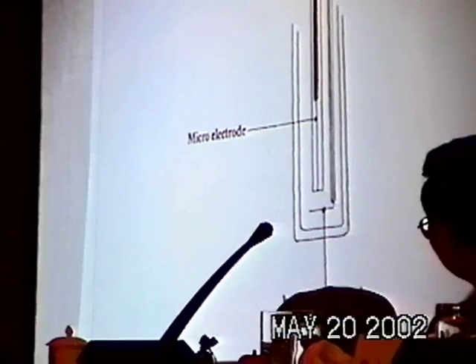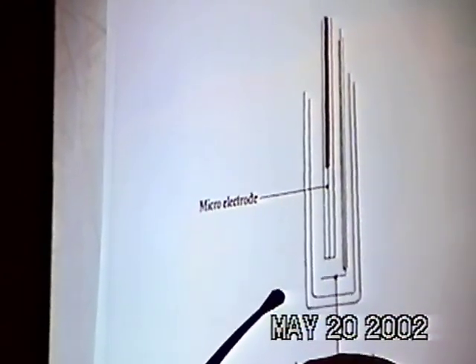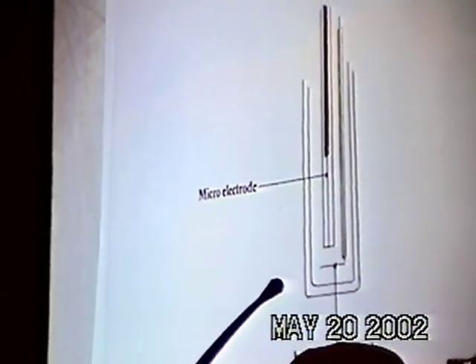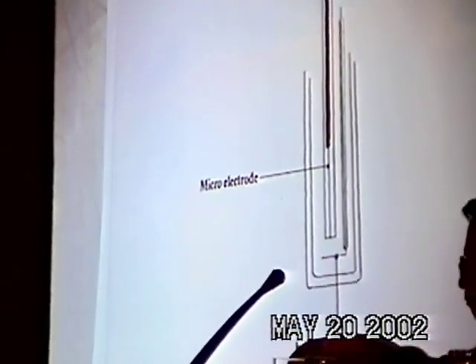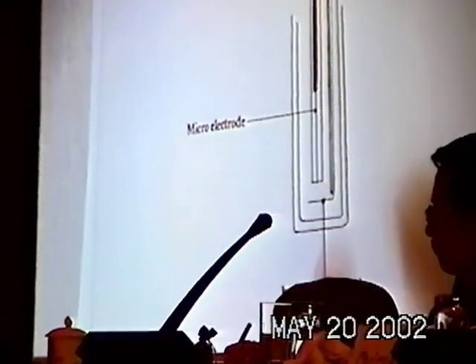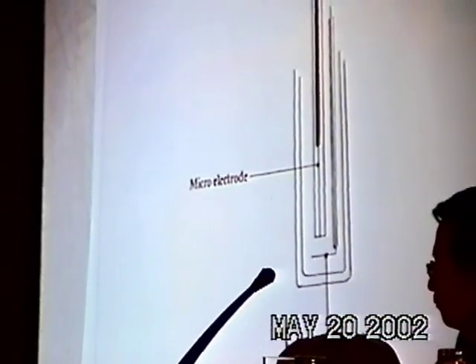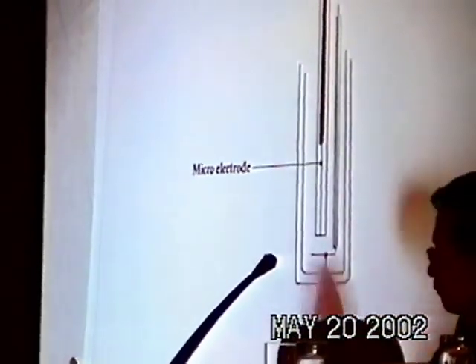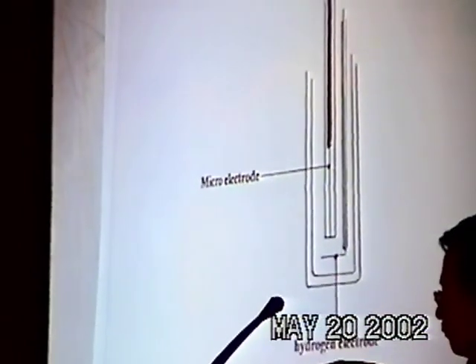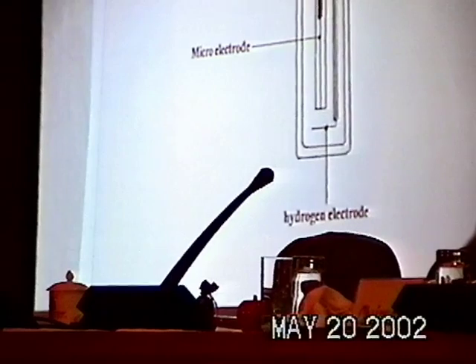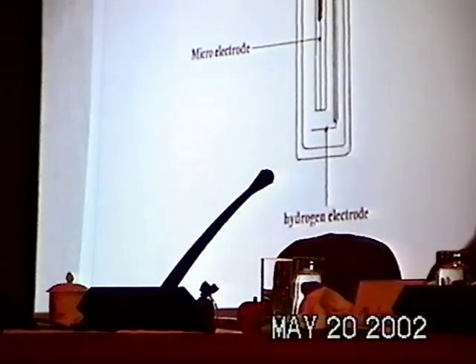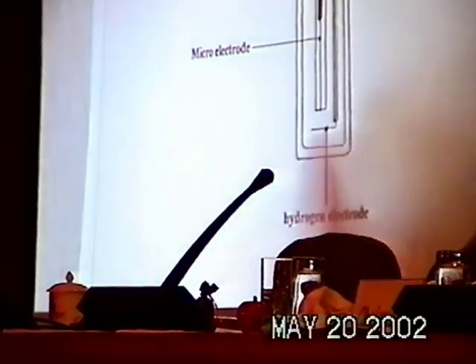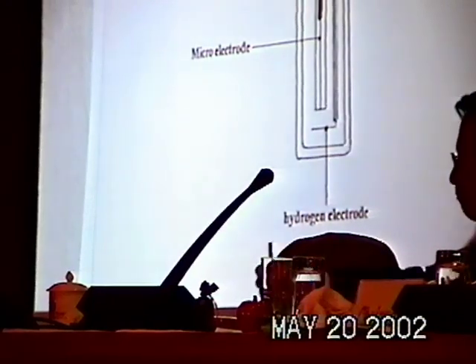The reason, of course, is that if you have a microstructure, then the joule dissipation of heat is reduced by orders of magnitude compared to a planar structure. So if you have an array of microstructures, you will get a much lower input of energy, and the excess energy will become much more visible. In fact, if you do the calculations on this, you come to the conclusion that you might very well be able to make a device which gives you the Q value directly. That's the energy of the nuclear process involved directly. You polarize the system with a low current, you measure the excess energy, and you can relate the excess energy to the current, and you should be able to get the Q value directly. That experiment has never been done.